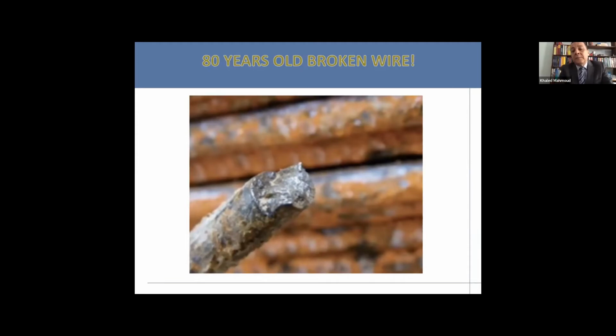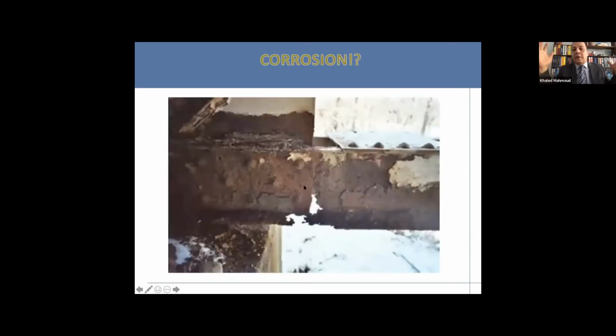And what you see here is a crack that starts at the edge of the wire, then propagates in the cross section, then the wire starts splitting along the longitudinal axis of the wire. That is the direction of the elongation of the grains, and then it gets broken here at this rugged surface. So corrosion, well, this is corrosion. What you see on the screen now is corrosion, because you have perforation, and by definition, the word corrosion means loss of mass, anode and cathode, and the corrosion cell, and we know that from early on.